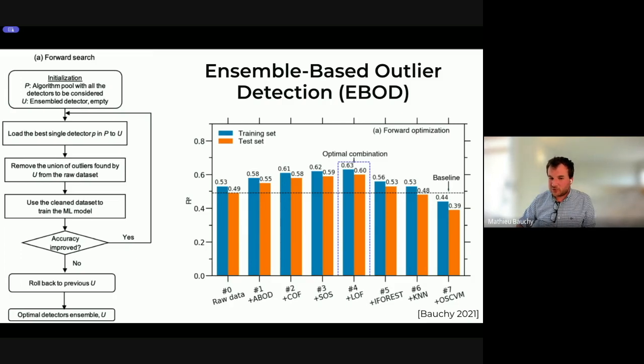And so what we typically observe is that as you start adding outlier detection algorithms, the accuracy starts to increase. And then at some point, when you start to remove too many outliers, the accuracy starts to decrease again, because you're starting to remove points that are actually useful for the model to learn the relationship between concrete constituents and concrete's performance. And so basically, that's where we know we have found the optimal combination of outlier detection algorithms. So that's the approach that we have been using. We call it ensemble-based outlier detection, so EBOD. And at least for the case of concrete, it has been an efficient approach to really find the best balance between cleaning the data sets, but without removing those data points that are actually useful for the model to learn how to make predictions.